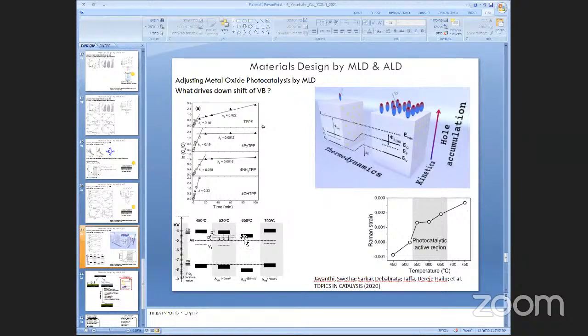One is the downshift of the valence band, and another one is that these defects are unique just to 520. The reason it is unique to 520 is probably a combination of thermodynamic and kinetic effects that occur while you anneal this system. On the one hand, you have the decomposition of the organic components, and on the other, you have concomitant crystallization of the oxide clusters. And at the end, there is some sweet point where you can retain structural defects that give rise to these